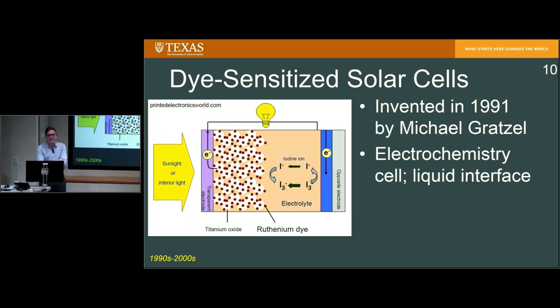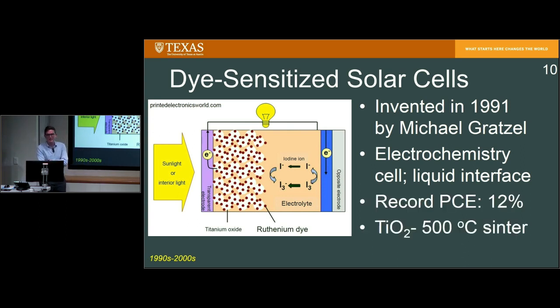The issue, though, is because he was an electrochemist, he used a liquid junction interface. And so it's not a real practical design if you think about putting this in the field for 25 years. Your electrolyte's going to start to corrode, or it will directly evaporate. You'll have issues with that. And so it became a bit of an issue. It never actually got to high PCE. And additionally, you couldn't really use it in flexible designs anyway, not just because of the electrolyte issue, but because the TiO2 had a 500-degree sinter associated with it to get nice quality films.